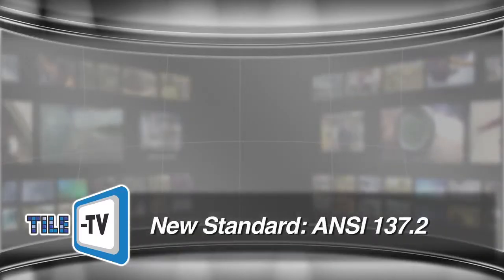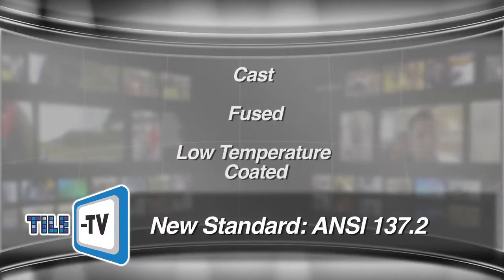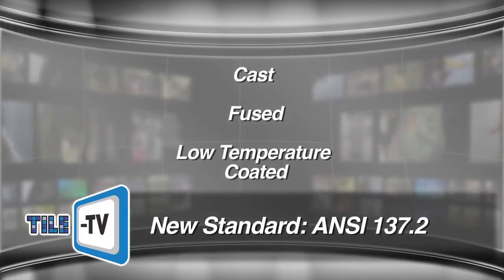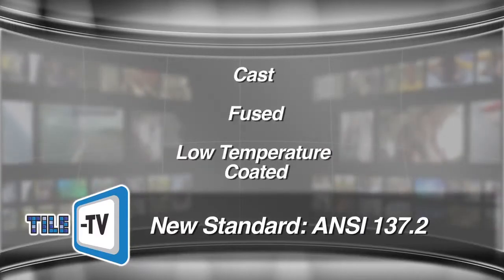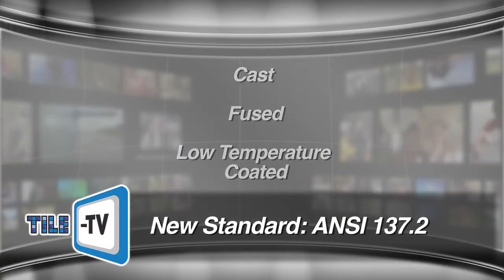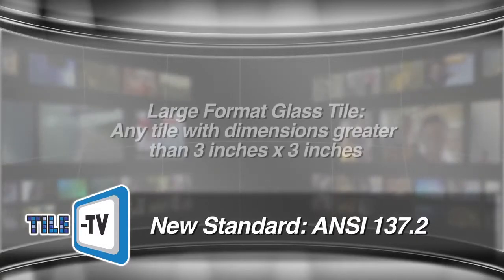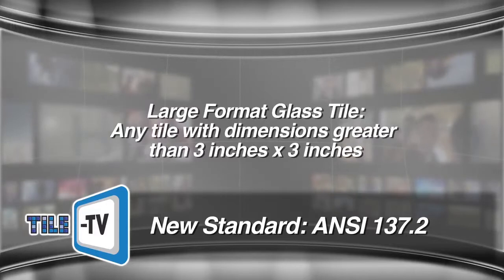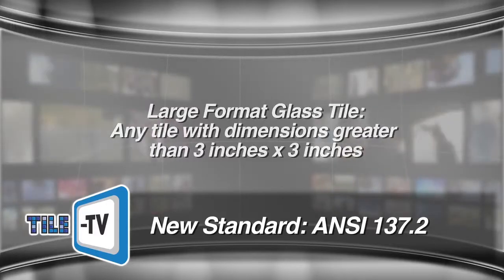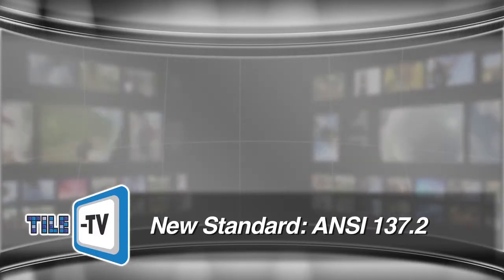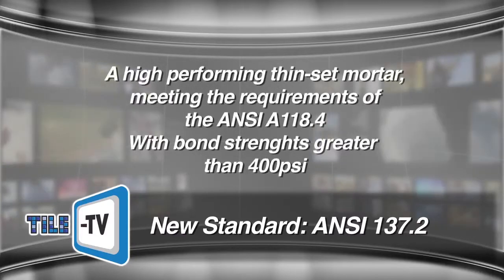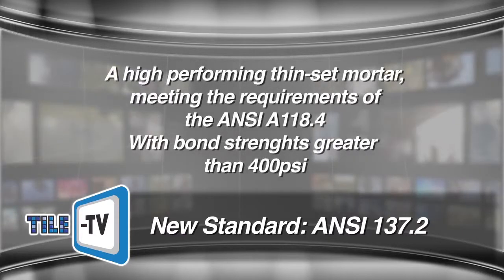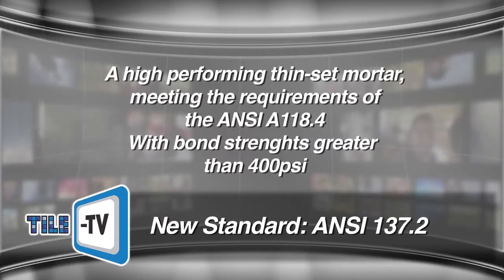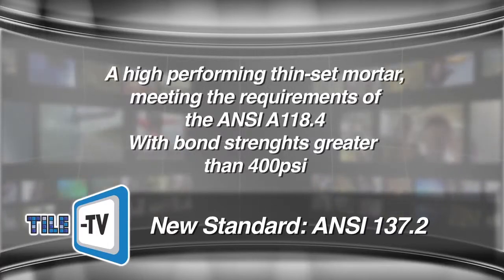The new standard identifies 3 different types: cast glass tile, fused glass tile, and low temperature coated glass tile. It also defines large format glass tile as any with dimensions greater than 3 inches by 3 inches. After all the testing and review of these tiles, the standard recommends the use of a high-performing thin-set mortar meeting the requirements of ANSI A118.4 with bond strengths greater than 400 psi in shear bond strength.